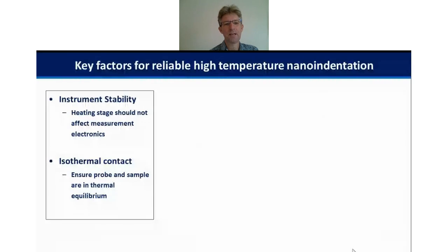So make sure that this heat does not reach your measurement electronics and give you some sort of control unit drift. But equally important, and perhaps more important, is that you need to actually control the temperature in the contact to ensure that the probe and the sample are in thermal equilibrium, so that when you do an indentation test, you don't get heat flow as your dominant measurement, and you actually measure the deformation of the material and not the thermal drift of the contact.